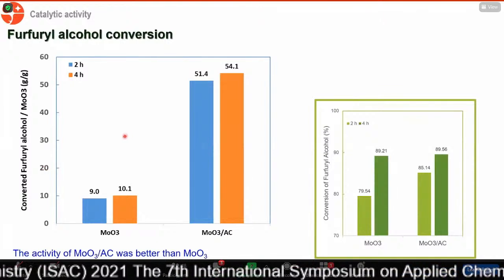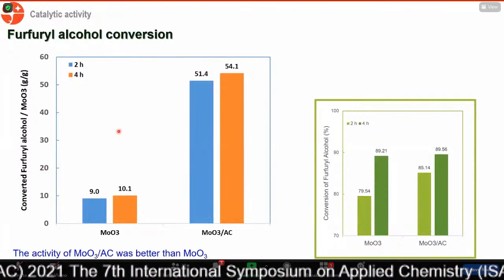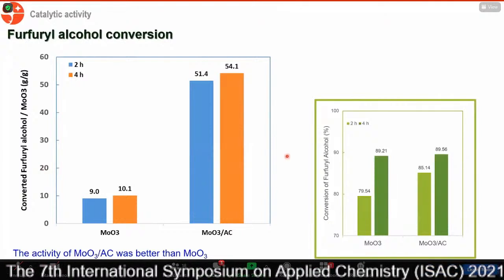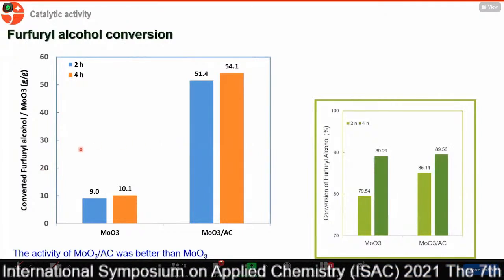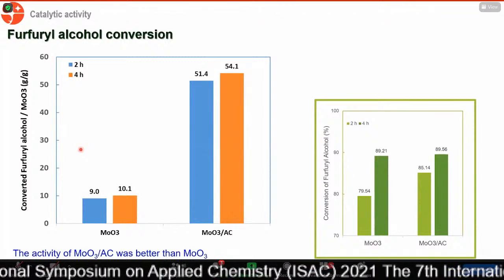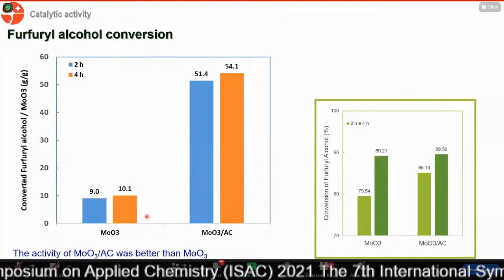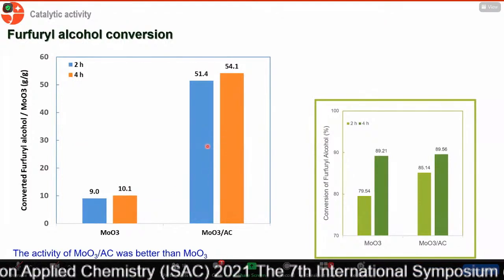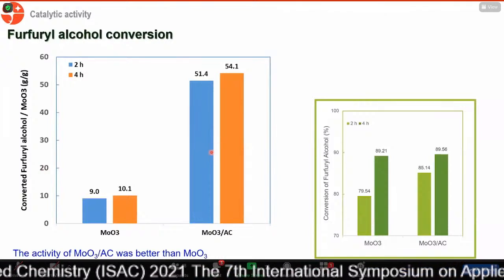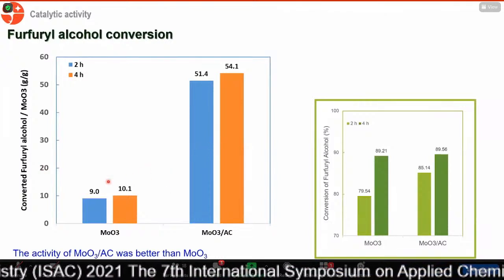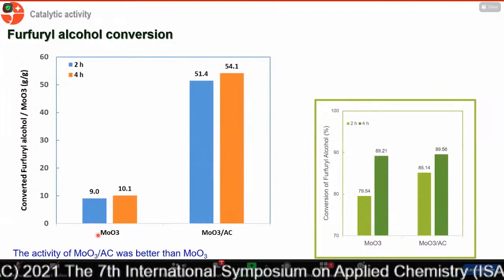After the reaction, we measured the conversion of furfuryl alcohol. After normalization with the amount of molybdenum oxide, we can see here that the activity of our supported molybdenum oxide is much higher, about 5 times compared to the bulk molybdenum oxide.